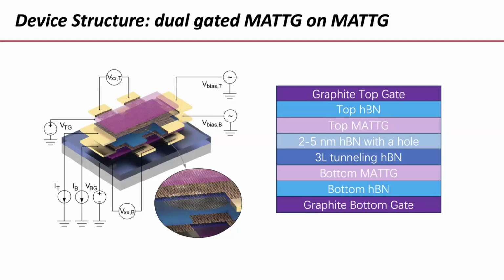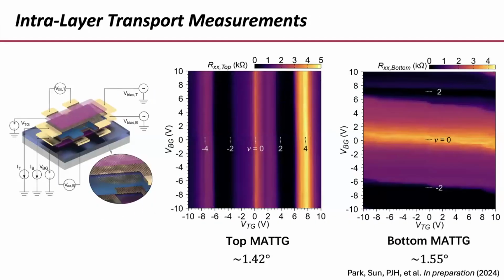So this means that, because each of the magic angle tri-layers has a Hall bar shape, we can do intra-layer transport of the properties of the magic angle tri-layer graphene in each of the two layers. And we can also do interlayer tunneling experiments so that we can probe one with the other. So we can do transport in plane in each of the layers, and we can do transport between the layers, which is actually tunneling because we're going through the tunnel barrier. Let me show you the intra-layer transport for each of the layers.